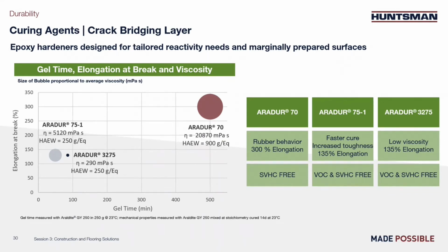Aradur 3275 is also very low in viscosity, but what we observe is that toughness is better with Aradur 75-1. So if you want to put filler, of course, Aradur 3275 would be better, but for toughness, 75-1 is more interesting, I believe.